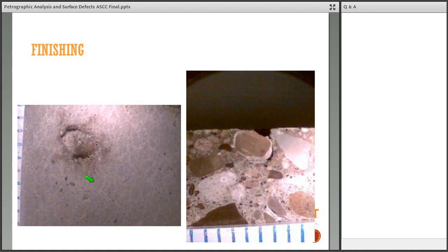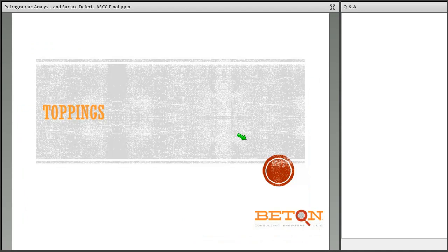You can make a mistake. A colleague of ours many years ago identified this as an ASR pop-out. In actual fact, it's caused by a different phenomenon. You can see the little micro cracking all in here, where this particle has been torn and is free to move at the base because it's setting at the surface ahead of the rest. And it was nicked by the blade, and the blade has picked it up and moved it around. And so we see that fairly frequently.